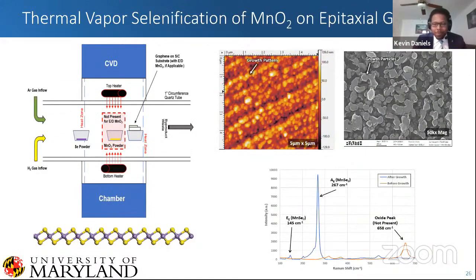And then just kind of a side note, we're actually able to take that electrodeposited manganese dioxide and form a different material, manganese diselenide, which is a ferromagnetic material, by basically popping our manganese dioxide in a chamber with some selenium and doing selenization on the material to form this thin film ferromagnetic material.